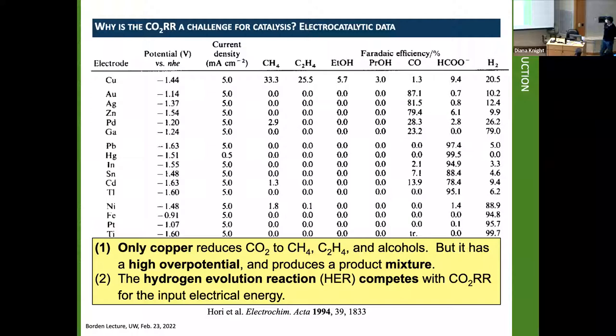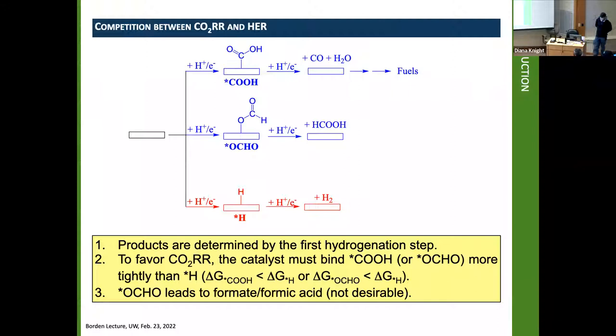And finally, the last two columns are also important. The second last column is formate, in other words, the conjugate base of formic acid, and hydrogen. It's quite easy to reduce protons to hydrogen. That will happen on almost every metal. And it's fairly easy to reduce CO2 to formate. That will happen on many surfaces, but we don't really want formic acid. There's not a good formic acid fuel cell, for instance. So copper is important, and selectivity is critical. We want to make sure that the first transfer of a proton and an electron favors *COOH over *OCHO over *H, because the bottom channel leads to hydrogen, the middle channel leads to formic acid.